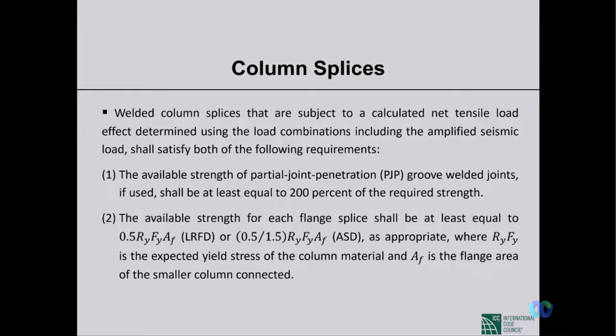And the conditions are, one, the available strength of partial joint penetration groove welded joints, if used, shall be at least equal to 200% of the required strength. So from the calculation of the loads, the amount of load that is coming onto that section, the capacity of the PJP joint should be twice of that when we are taking amplified seismic load. So we are that conservative about columns. Okay, we don't want hinges to form in the column. That's why we are so conservative. The available strength of each flange splice shall be at least equal to half of Ry Fy Af, that is, flange area multiplied by yield strength multiplied by expected strength factor.